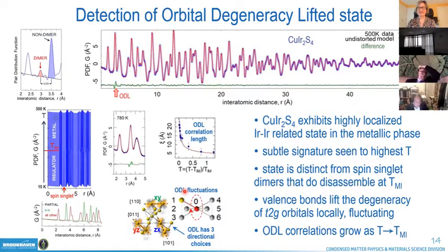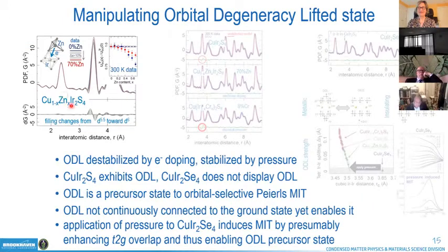Fine. But that was not enough. Of course, we wanted to prove to ourselves in the first place that this is an electronic effect. And so we embarked on a series of studies using judicious substitutions. So the first thing that we did was we doped zinc on the copper site. Zinc in tetrahedral environment solely comes as 2+ and represents basically electronic doping. And so as you dope electrons, what you see is that this peak, which is 95+% coming from iridium-iridium pairs, dramatically responds. And it responds in such a way that when you go from 0% zinc, which is blue, to 70% zinc, which is red, this distribution becomes narrower and sharper, which is to say that whatever distortion there was, it gets removed, which serves as a beautiful example of structural evidence of electronic doping, actually electronic transfer from zinc to iridium.